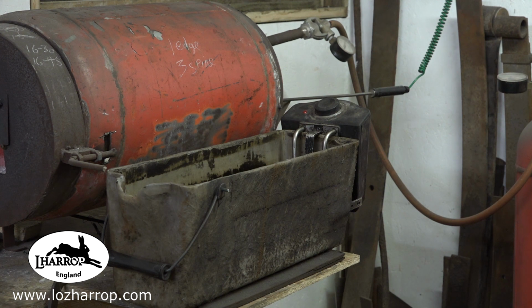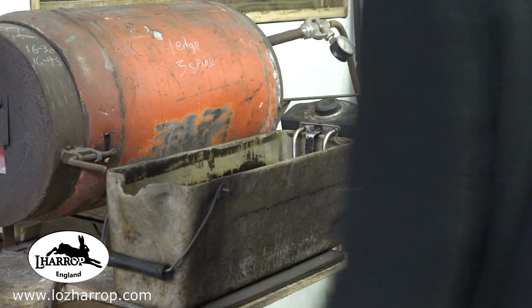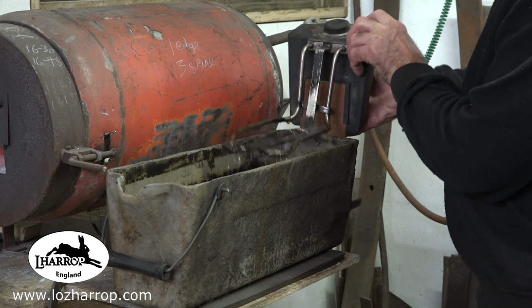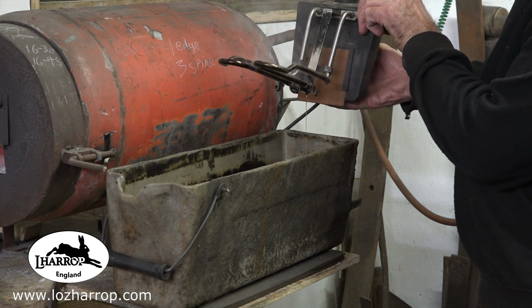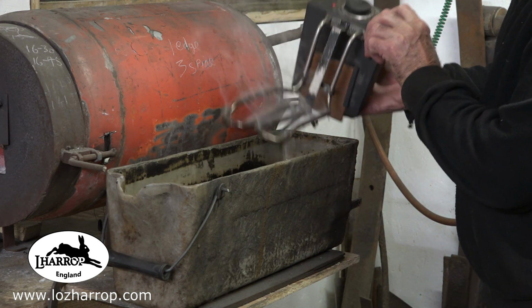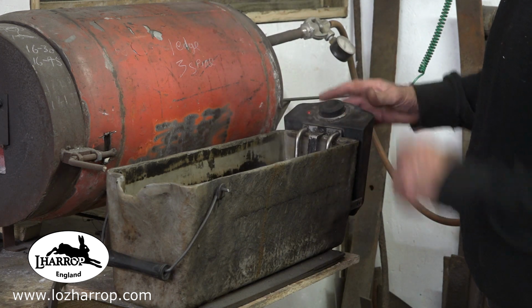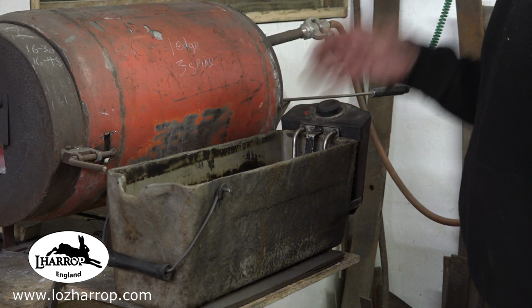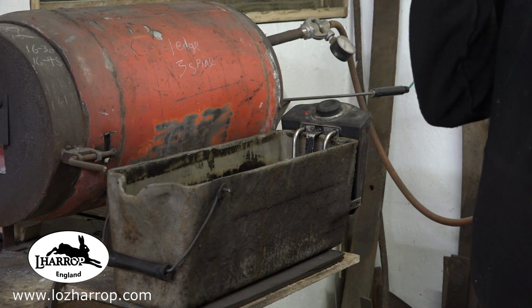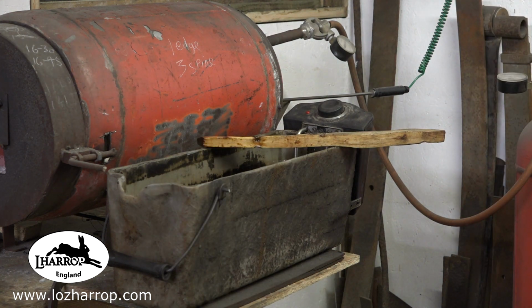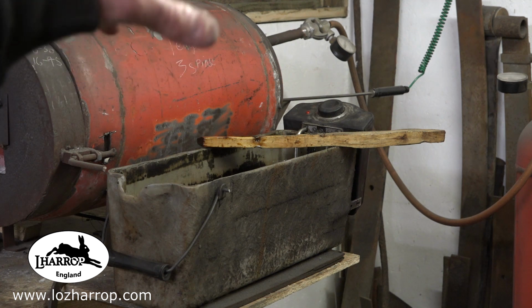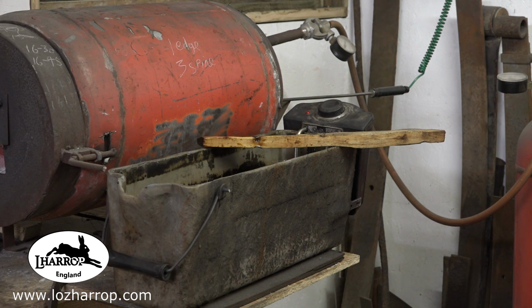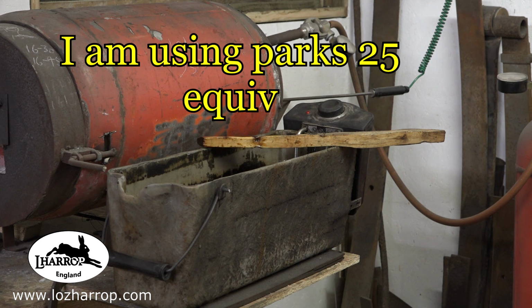So I'll start to heat the quench oil up now. I use one of these. These are kind of what you get in food fryers. Just fits perfectly in my quench tank. And I'll get the temperature up around 35-40 centigrade. It's a much better method than shoving a hot piece of steel into the quenchant, because doing that actually really reduces the life of the quenchant.